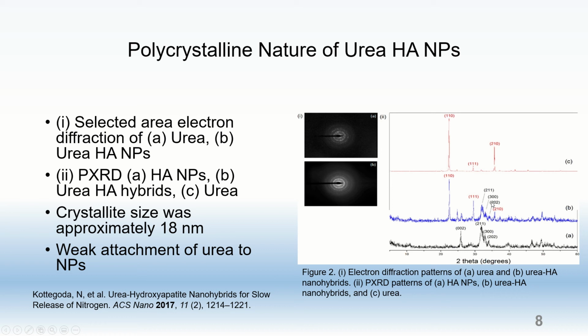Both of these figures help confirm the polycrystalline nature of the urea-hydroxyapatite nanohybrids, with figure 2.1b showing the rings formed by the many crystallites present in the sample, and figure 2.2 showing the broad and low intensity peaks in the PXRD patterns. The crystallite size was found to be around 18 nanometers, which is consistent with the TEM observations of the average size of the nanoparticles.